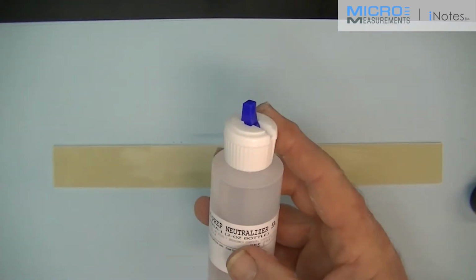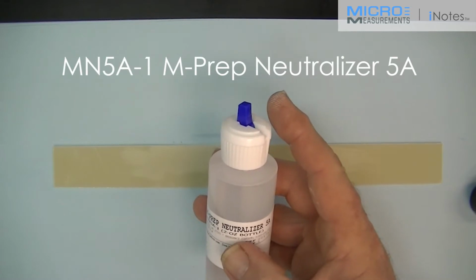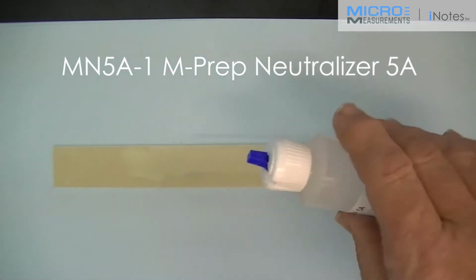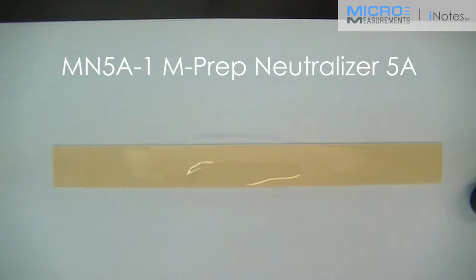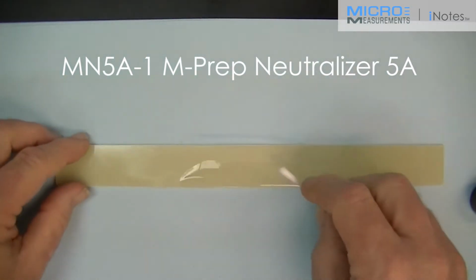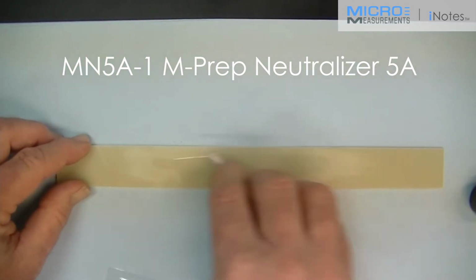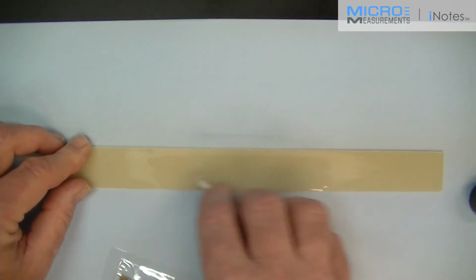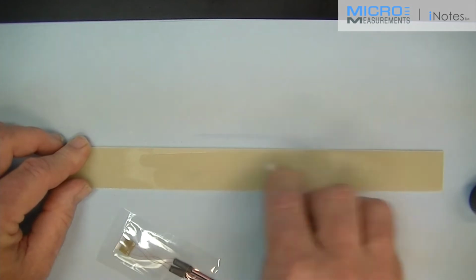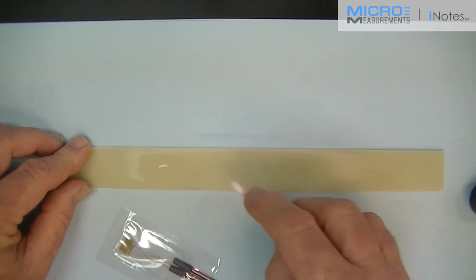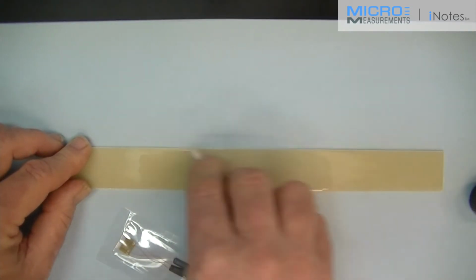The next step is the Neutralizer 5A. We're going to scrub with the Neutralizer 5A, an ammonia solution. Again, flood the surface of the beam. We don't want this to dry while it's on the beam. It would just redeposit the contamination. And then we're going to scrub with a cotton tip applicator. Again, keeping my finger behind the butt of the cotton tip applicator, I'm going to use sufficient force.